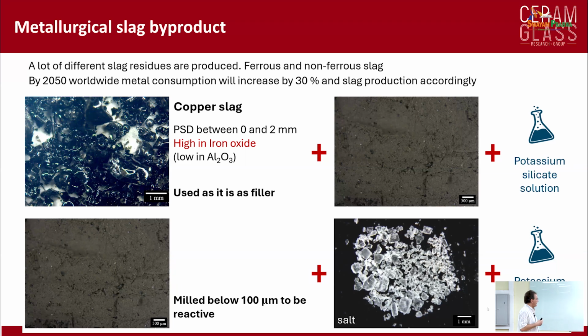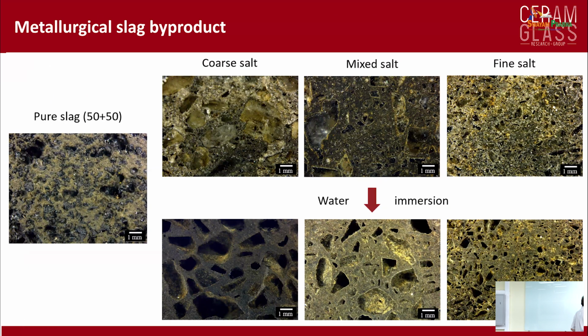There's a company in Sweden that makes a lot of this material. They sell it as a replacement for sand, but we wanted to use it as a reactive source of oxides that would enable the formation of a geopolymer. And if you remember, I mentioned that you can have iron silicate geopolymers besides aluminum silicate-based geopolymers. So this material was milled below 100 microns to be more reactive. And we are able to print and obtain a consolidated material.